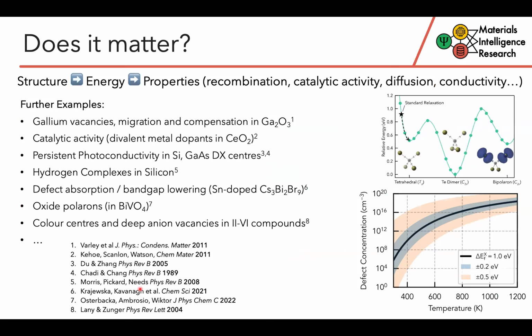So of course, I'm not the first to notice this behavior. The importance of defect geometries and potential metastabilities has been noticed previously in literature. So these are just some examples. But the point is that whenever this had been noticed before, it was essentially always what we would call serendipitously, so just by chance, lucky discoveries, or from some sort of manual searching that was performed after initial theoretical predictions strongly disagreed with some known experimental behavior. So people went back looking for it.